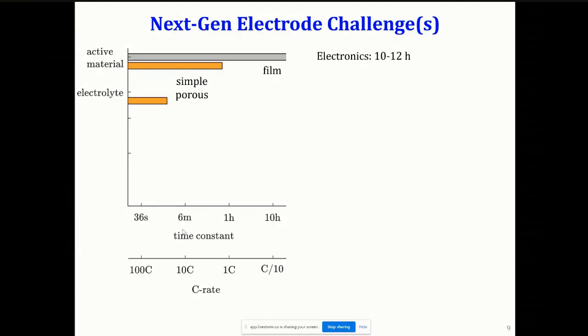So historically, first lithium-ion batteries were introduced in electronics, and that right now is about 10 to 12 hours of discharge life, right? That's your battery capacity you are looking at, which means that you are in about C/10 range, and which would mean that you are now limited by only the solid state diffusion. Your electrolyte diffusion limit is much farther. Second thing we look at are electric vehicles. If we are in US, we want about a couple hundred miles of range, and that boils down to about 6 to 8 hours of discharge time. And that would also give a little bit higher C rate, a little bit higher current, but still similar time constants, right?